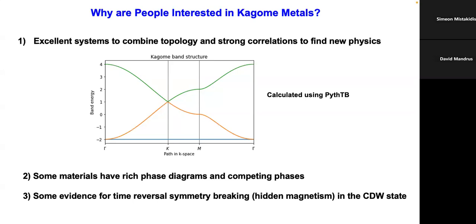And one thing that surprised me a lot: here's the simple tight binding calculation of the band structure of the kagome lattice. You can see there are three features. This is called a Dirac point. This is called a Van Hove singularity, right here at the end point. And this blue band here is called a flat band, and that comes from destructive interference of wave functions. What absolutely blew me away is that in real materials, this simple band structure survives to some extent. There are other bands in play, but you can pick out these features in the band structure. So that physics is surviving in real materials. They're good systems to combine topology and strong correlations.